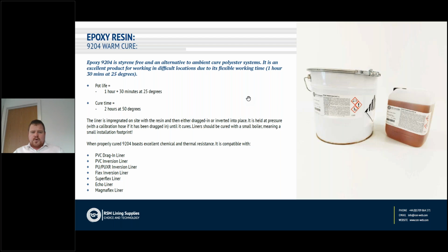It can be impregnated on site and generally requires quite a small installation footprint, because we can cure 9204 either with a small steam boiler or a small hot water boiler. Again, it has the same benefits as 9052. It can be used with our full range of drain liners for the dragging application, inversion. It can also be used with our flexible liners for applications where we have 45 and 90 degree bends. Again, the product is completely leak tight and has good chemical and thermal resistance.